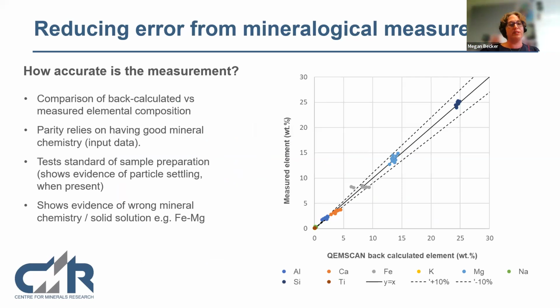Then we have this question about how accurate the measurement is. So what is standard practice? For many, and not necessarily all, but I do this all the time on any mineralogy data we report, we take the mineral grades that we get, apply a mineral composition, and back calculate an element concentration. We then measure this with some other assay technique, XRF or ICP-OES, and we plot this parity chart. Over here, I've shown the 10% line, so 10% above and 10% below. Ideally, if we say we're going to work within 10% bounds, we want all the back calculated numbers to sit within a 10% window.